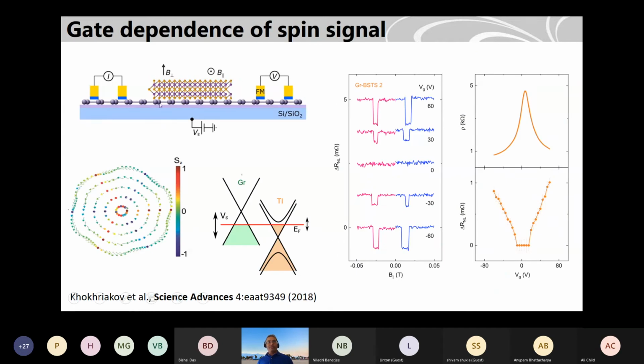So this is again the experimental setup. As I showed, we pass the current here, so we inject spin into graphene from this ferromagnet. The spins go along this channel and we detect the voltage. And this is how the spin signal looks. What we see is that when we apply the gate voltage, it is quite tunable, and that can come from different experimental factors. I will not go into details.